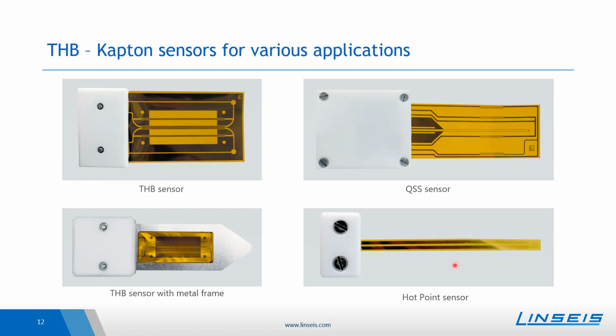And for very small and especially also for anisotropic samples, we have the hot point sensor, which has only a very low sensor area. So here just the tip needs to be covered, which is about 2 × 2 millimeter. For the other sensors, there's the requirement that the sample needs to cover the complete sensor foil. So here for the THB sensor, we have two versions. One is about 25 × 45 millimeter, and the other, the larger sensor, has a sensor area of about 45 × 85 millimeter. The QSS sensor is also for about 25 × 55 millimeter large samples. So here also the requirement is that the sample covers more or less the complete sensor foil. Only for the hot point sensor, just the tip needs to be covered.